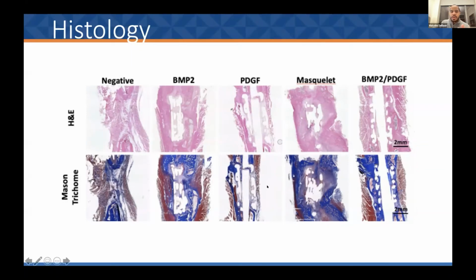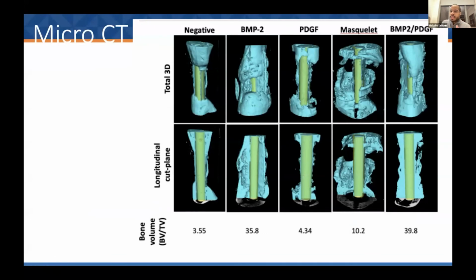So then, when we looked at our micro CT, similar type outcome, but BMP looks like our winner here, both in BMP only and the BMP with the platelet-derived growth factor. Both of those groups healed nicely and had some pretty good bone volume quantitatively.